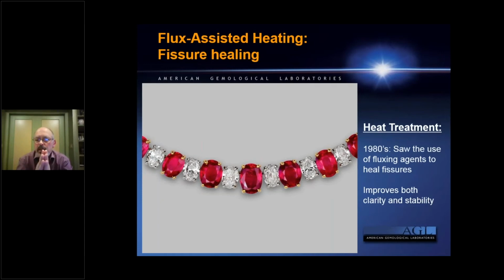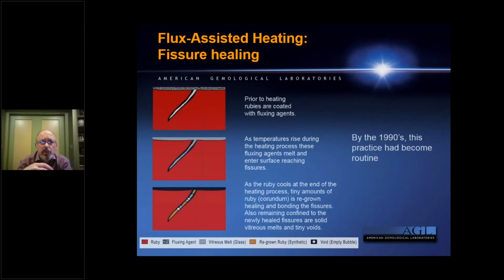And so this healing of fissures actually serves a couple of purposes. It improves the transparency by reducing the visibility of the fissures. It also improves the stability of the stones somewhat. That's why they commonly heat them in the rough, because trying to fashion them in the rough state, stones may not always survive the cutting and the polishing process. So they heat them with the fluxing agents to help really bond the material together. And so this is the next part that we're going to talk about.